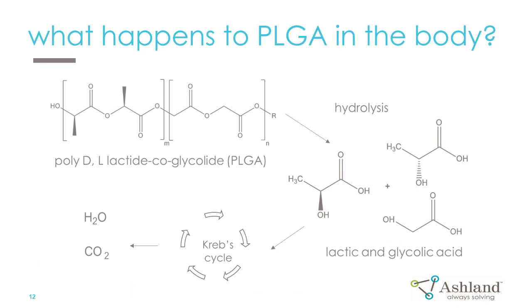We're using a chemistry that the body really well responds to and understands, and we're delivering polymers based on a programmable system that you can be consistently reliant on. The most important thing to take from this slide is hydrolysis. So everything that you do in terms of handling, so when you store it in a sealed pouch, in terms of processing when you work on an extruder, or in terms of sterilization or post-processing applications, you always need to be conscious and mindful of water and how water can damage these chemistries. So try and resist water, try and remove it from all process steps, and repel it where possible in your application from start through to finish, and you will achieve a better outcome and a more consistent, stable system.